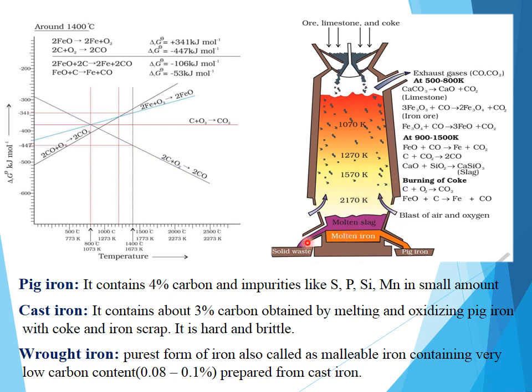So from this blast furnace, you will get pig iron, which contains about 4% of carbon, and it contains some impurities like sulfur, phosphorus, silicon, and manganese in small amounts. If you want to reduce the percentage of carbon, again this pig iron is treated with coke and iron scrap, where it is further reduced to 3%, and whatever iron we get at that time, we call it cast iron.